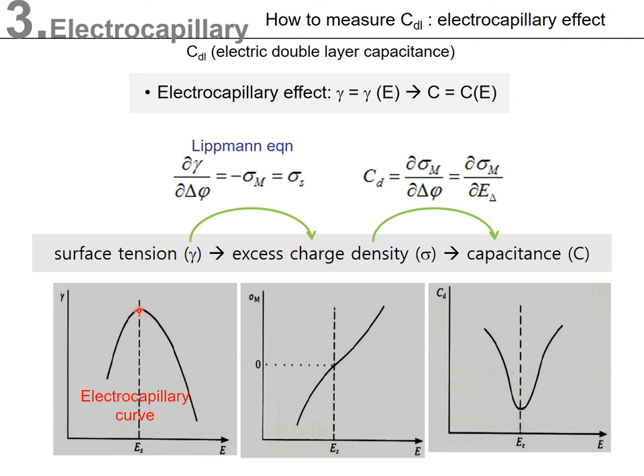At the point of zero charge, I have said surface tension was maximized. And then when you apply a potential, due to the repulsive forces between the same charges, the surface tension goes down with your droplet being extended along the surface. At the point of zero charge, capacitance is minimized, of course, because there is no excess charge. However, when you increase or decrease the potential, your capacitance would increase. So finally, we obtain the capacitance as a function of the potential.